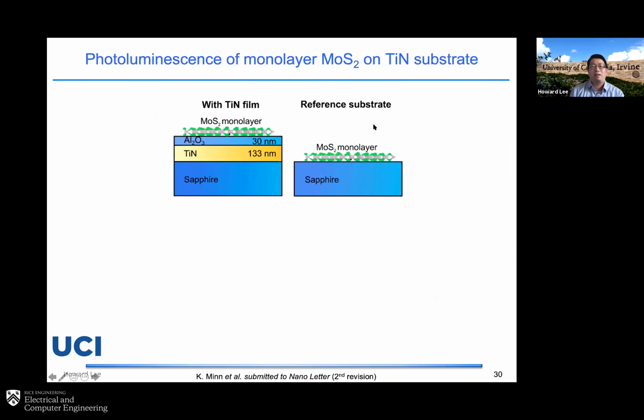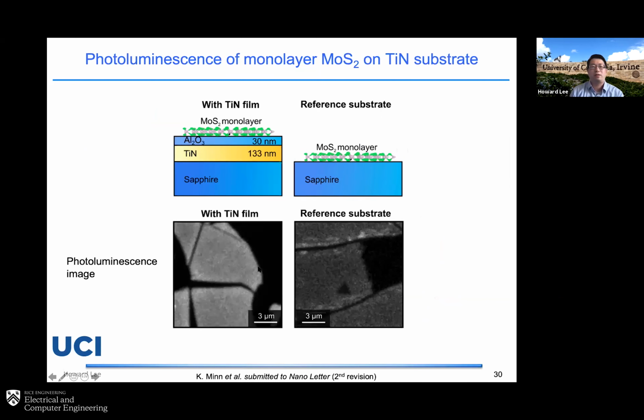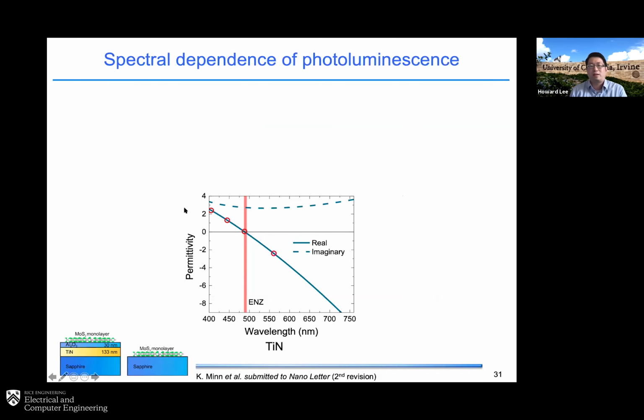So the study basically is quite simple. Again, we have a MoS2 emitter, oxide, and then the ENZ material, titanium nitride. And then we compare with a reference where we don't have the titanium nitride, basically with sapphire below as a reference here. If you take a look at the photoluminescence image, you can clearly see a stronger enhancement, stronger light coming out from the structure with the ENZ film below compared with the reference.